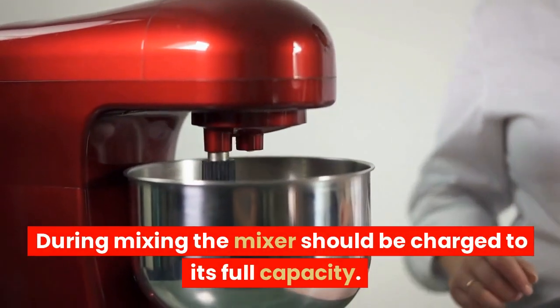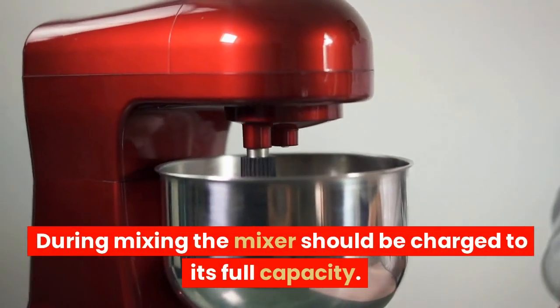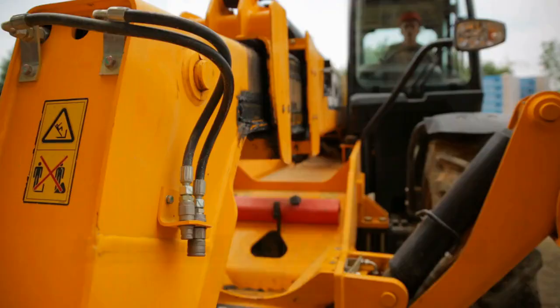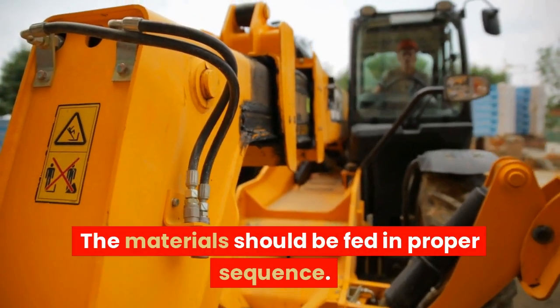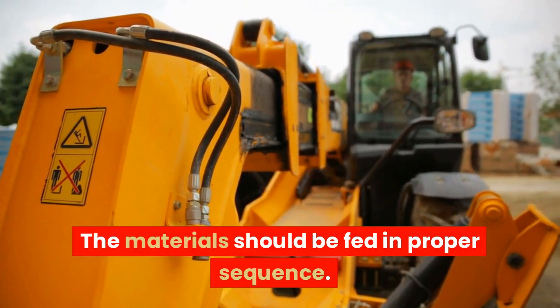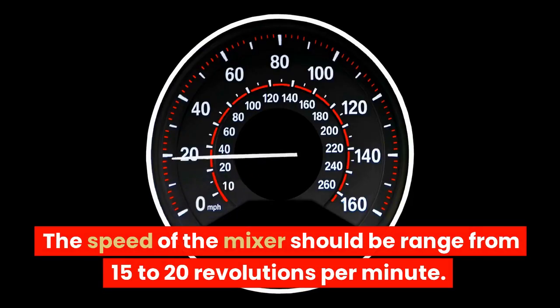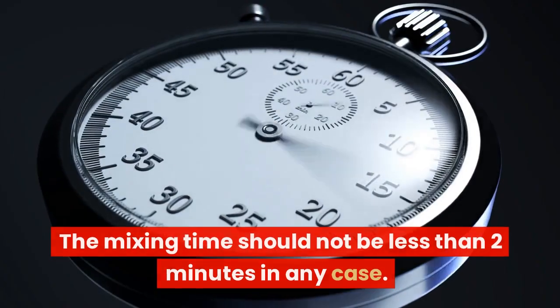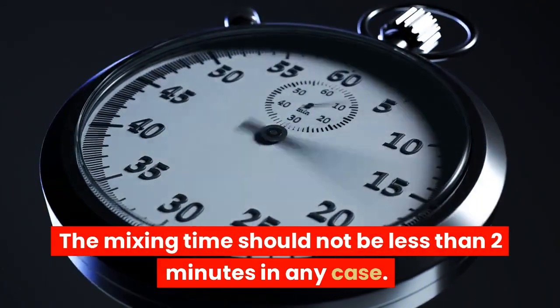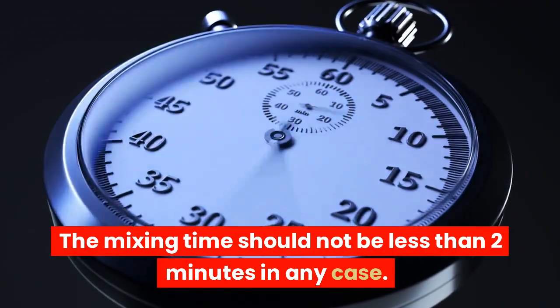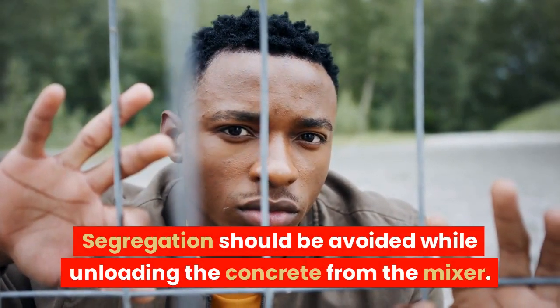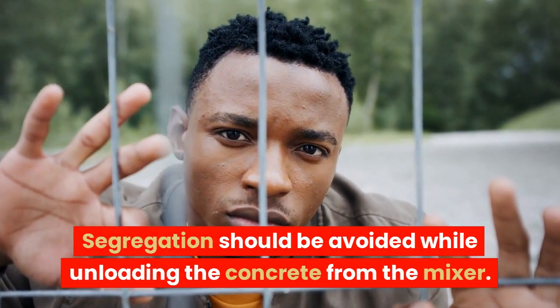During mixing, the mixer should be charged to its full capacity. The materials should be fed in proper sequence. The speed of the mixer should range from 15 to 20 revolutions per minute. The mixing time should not be less than 2 minutes in any case. Segregation should be avoided while unloading the concrete from the mixer.